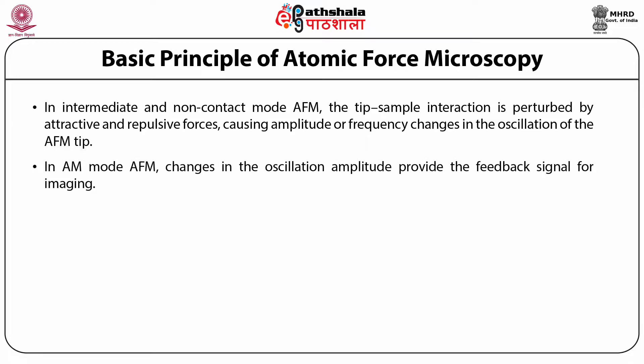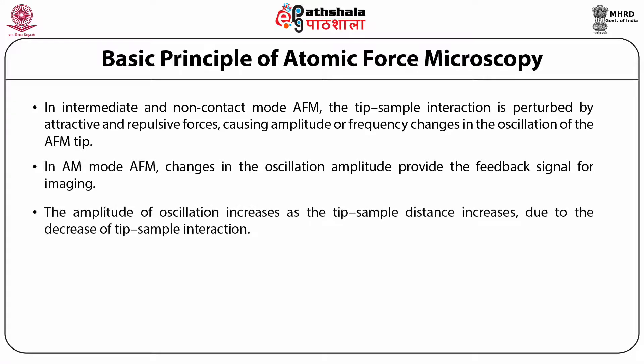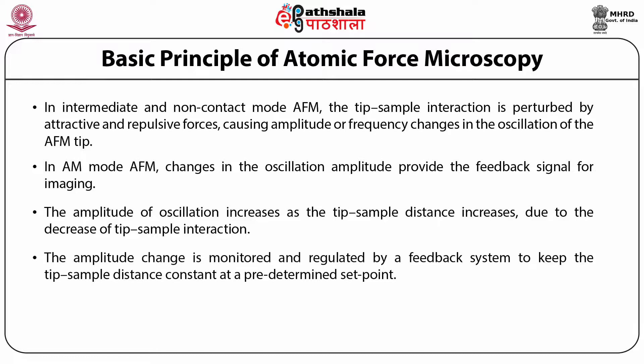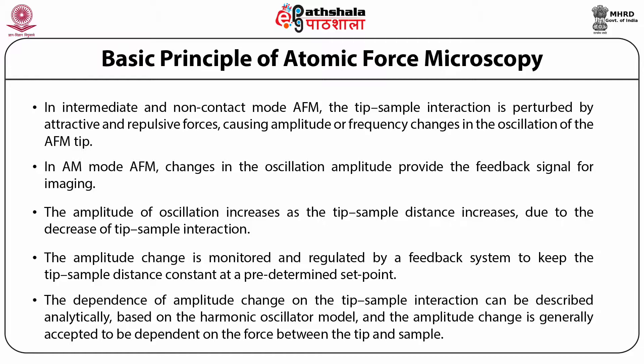In AM mode AFM, changes in the oscillation amplitude provide the feedback signal for imaging. The amplitude of oscillation increases as the tip-sample distance increases due to the decrease in tip-sample interaction. The amplitude change is monitored and regulated by a feedback system to keep the tip-sample distance constant at a predetermined set point. The dependence of amplitude change on the tip-sample interaction is described analytically based on the harmonic oscillator model, and the amplitude change is generally accepted to be dependent on the force between the tip and the sample.